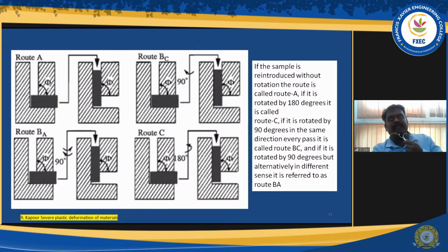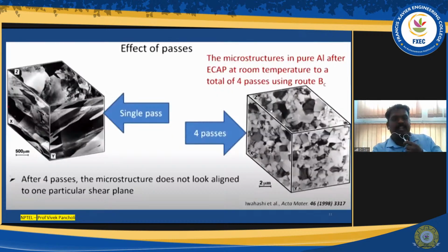So inside the material, that will give some bands that will help the fragmentation. For a typical example, here I showed an aluminum sample. The initial sample looks like very coarse grain. After 4 passes, you can see a very ultrafine grain size, in the range of 1 micrometer, right?